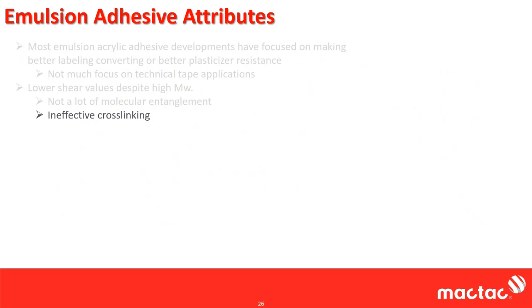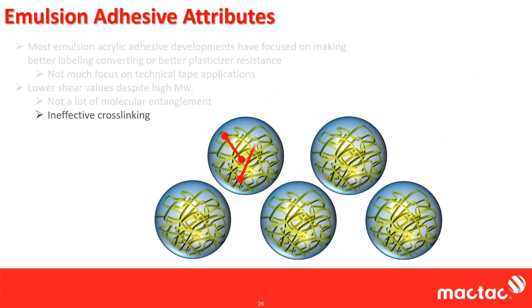Another reason why you don't see these used a lot in technical tapes applications is, I'm having trouble defining this, but I call it ineffective cross-linking. Essentially, despite some misnomers out there, you can actually cross-link emulsion adhesives. The problem is that when you add cross-linker, you get a lot of cross-linking that happens within the micelle. And a lot of the reason people cross-link emulsion adhesives is not to make them more cohesively strong, but to actually kill the tack and turn them into removables. This is something MacTac does on our roll label side a lot, where we use a lot of emulsion adhesives. We can add some cross-linker to them externally, and take a permanent adhesive and make it into a removable adhesive.